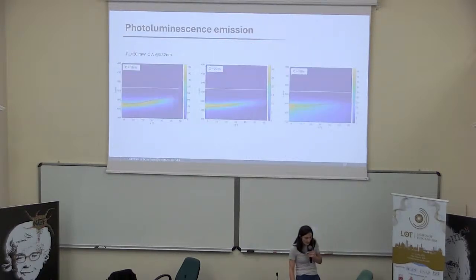From our cavity we also study photoluminescence emission. This is quite important. We want a large strong coupling, but we also want to preserve photoluminescence efficiency. We pump our system above the lower polariton branch using a CW laser, and we observe efficient recombination from the lower polariton branch for a certain range of concentration, here up to 50%.